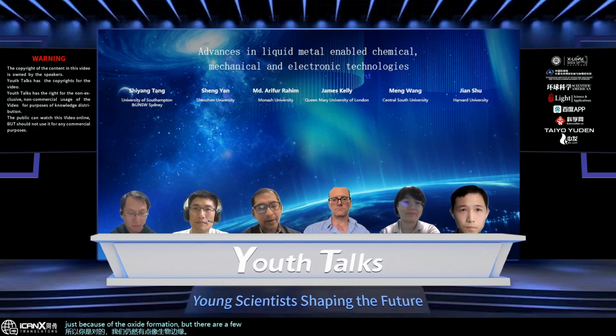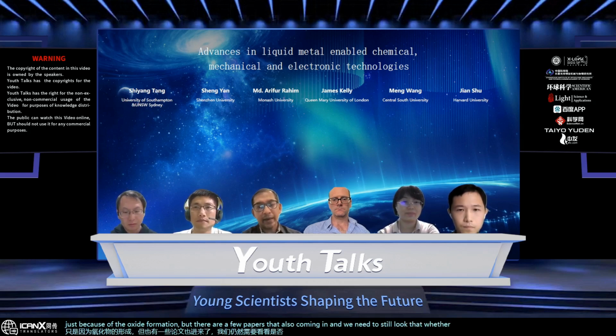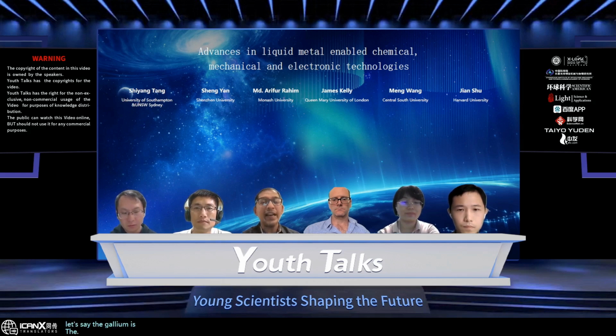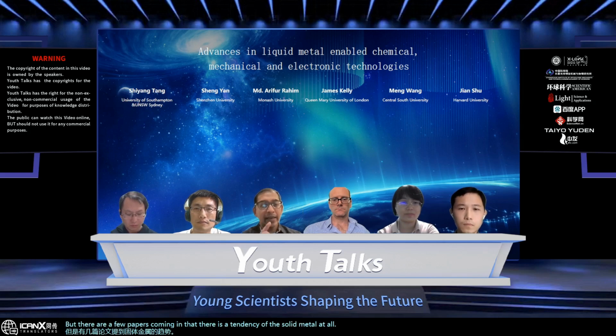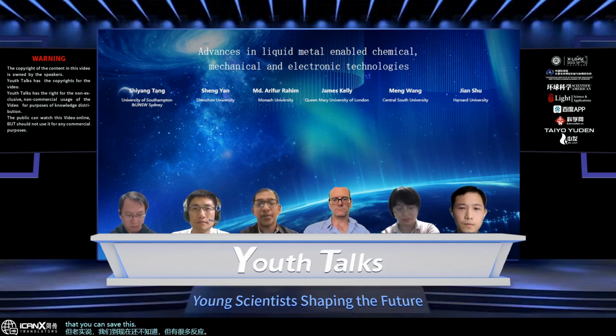But there are a few papers coming in, and we still need to look at whether gallium is inactive, which is not absolutely true, but let's say it acts just as a liquid matrix. There are a few papers suggesting a tendency of the solid metal atoms to penetrate that oxide layer a little bit if it is thin enough. But honestly, we do not know up until now. There are many reactions where you can set these conditions in a way that you can avoid the oxidation.